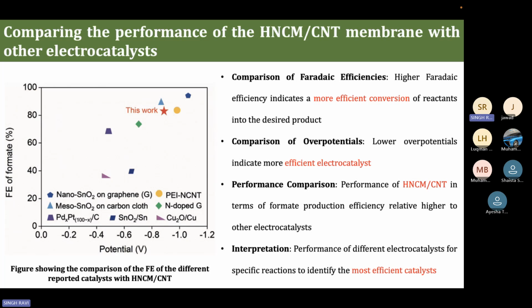And comparing this result with the other catalysts which were reported previously, we can see that this catalyst is not so high as compared to the other catalysts, but it's quite good enough, where the Faraday efficiency of 81% of formate was formed. But in terms of other catalysts, they are metal doped and this is a non-metal doped catalyst. So in this case, we can see that the carbon catalyst can also be a very promising catalyst in the near future if we try to use it in a good way, like modifying its morphology and trying to find the good active site of this catalyst, then it can be very good in the near future.